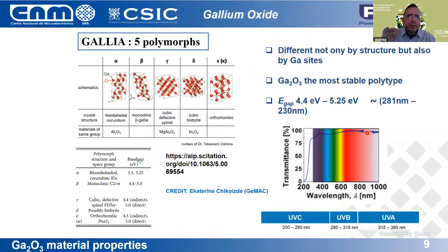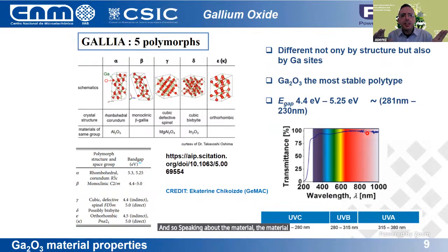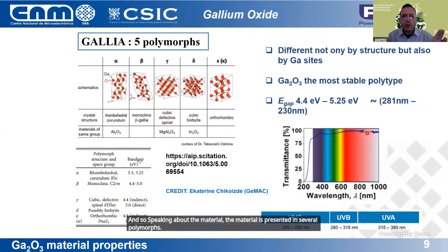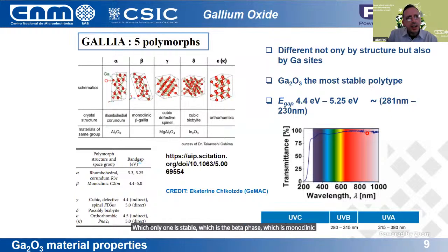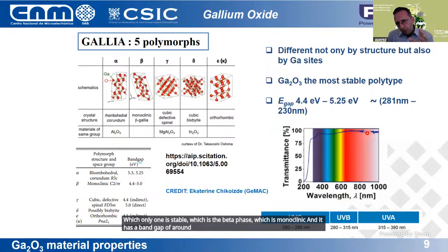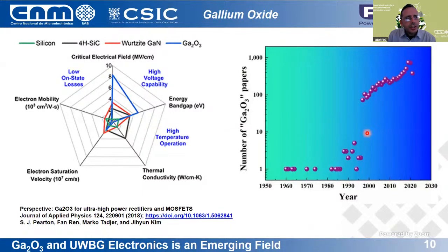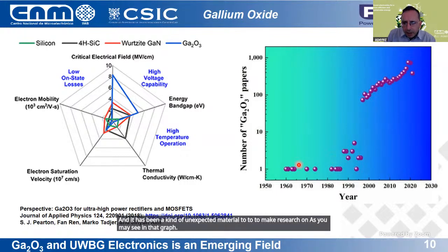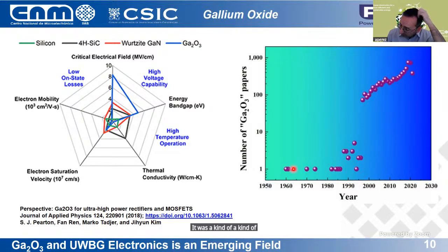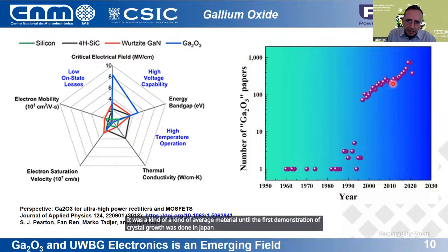So, speaking about the material, it is presented in several polymorphs, of which only one is stable, the beta phase, which is monoclinic. And it has a band gap of around 4.8, which means that it is completely transparent to the visible spectrum. And it has been a kind of unexpected material to do research on, because as you may see in that graph, it was a kind of average material until the first demonstration of crystal growth was done in Japan, and then it attracted a lot of interest.